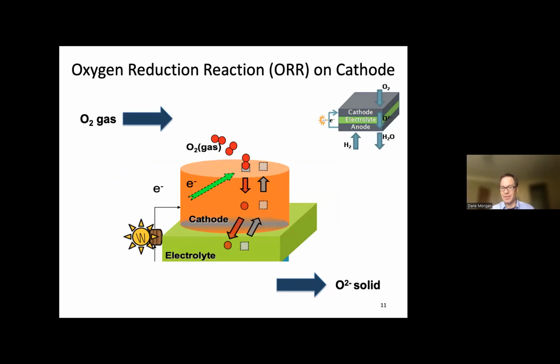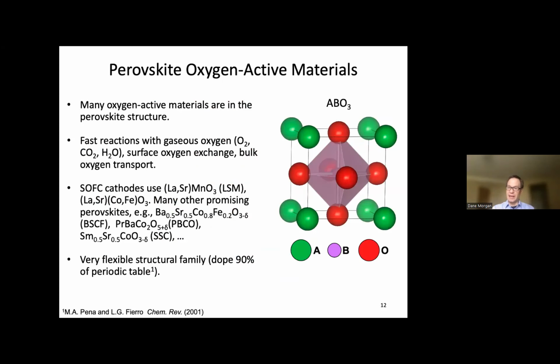So here's a kind of schematic of some of those processes. Oxygen comes in as a gas, an O2 molecule. It's got to somehow split up into two oxygen. And generally, that is believed to take place by interacting with some vacancies on the surface. So you're going to hit the surface, maybe diffuse around, react with vacancies, and then move in those vacancies. Once you fill a vacancy, you're going to move by diffusion through the cathode and then down into the electrolyte as an oxygen ion. So this is essentially the process we are trying to understand, and we're trying to build materials that can do it quickly and efficiently.